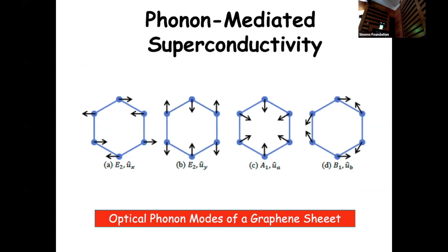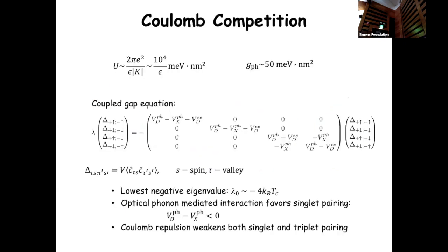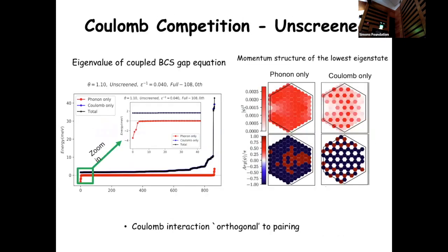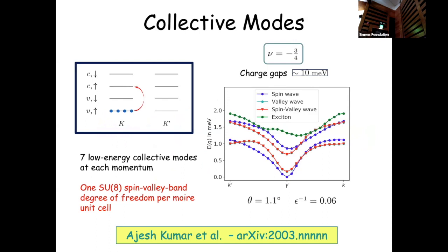Here's, when you come to superconductivity, a straw man for superconductivity in twisted bilayer graphene. You could imagine the possibility it's mediated by these optical phonons. That's like the superconductivity in intercalated graphite, which is basically mediated by interactions with these phonons. And you can imagine if you get the high density of states, that can happen here as well. But the competition with Coulomb interactions,